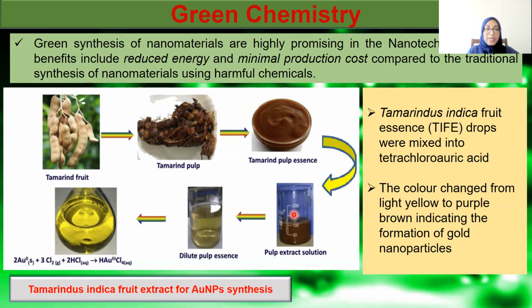For the preparation of tamarind indica fruit extract, a small piece of tamarind indica fruit was kept in 50 milliliters of hot deionized water for 5 minutes. Then this tamarind was squeezed well. The extract of this fruit was then filtered and stored. The tamarind indica fruit essence drop was mixed into the tetrachloroauric acid. Then the color changed from light yellow to purple brown, indicating the formation of gold nanoparticles.